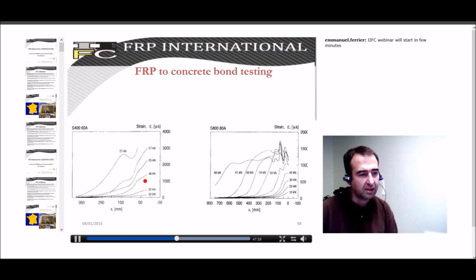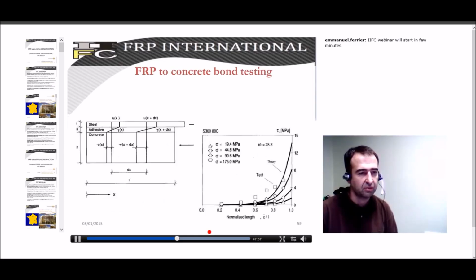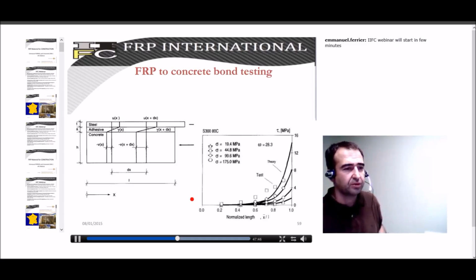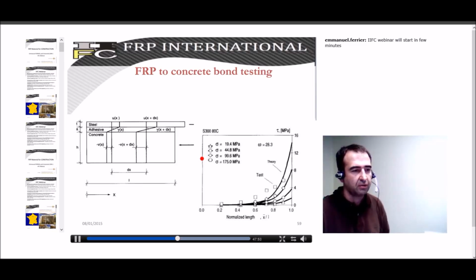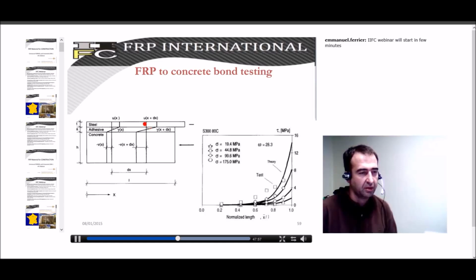But in the elastic stage, the bonding length is not so long. We only need 100 to 200 millimeters to bond this material onto the supports. This is mainly due to shear transfer. This is also shown in some older studies done mainly in the field of aeronautics, with authors like Volkersen or Hart-Smith.